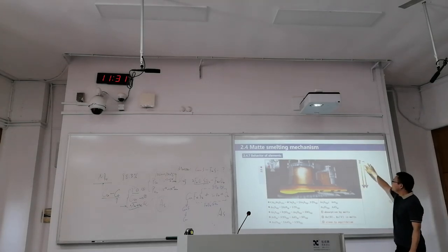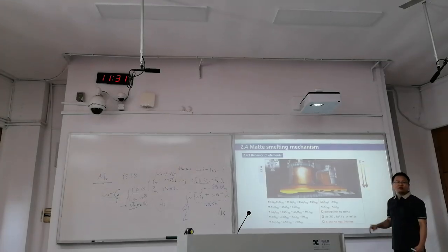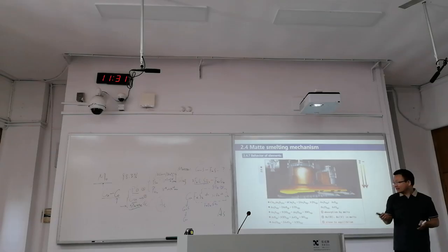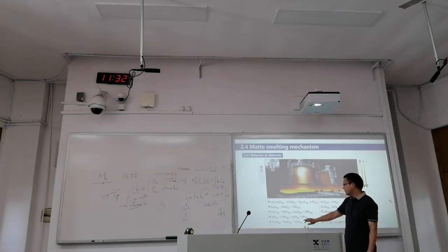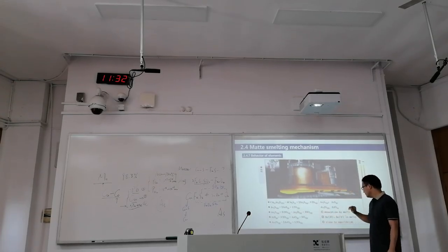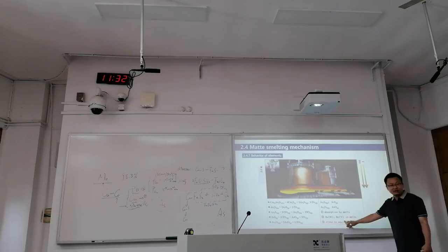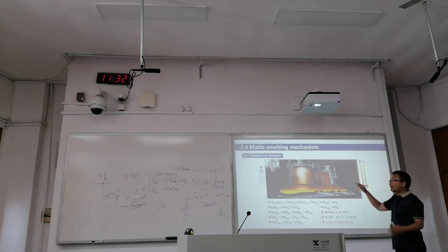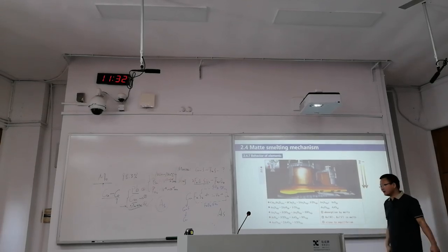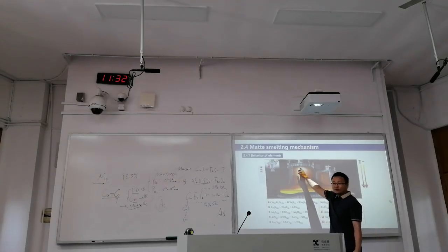And we have plotted these two arrows. So this is high temperature, low temperature, high oxygen potential, low oxygen potential. Do you still remember that? When we are oxidizing arsenic, when arsenic is in a high oxidation state, probably As(V), it will be more stable. And the formation of arsenic 5 will be accelerated with high temperature and high oxygen potential. So it will have less tendency to go to the gas phase. And another point here, this is the hottest region.